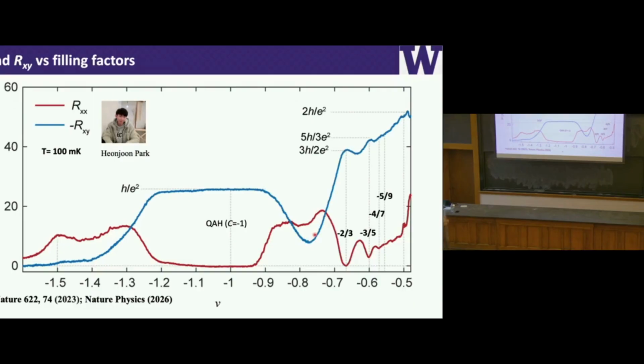So what it means is that it's a ferromagnetic metal phase, but with partial filling of a flat Chern band. And then we keep doping, and reach the 2/3 filling. Now we have a vanishing Rxx again with Rxy quantized at 3/2 of h over e squared. So that's my 2/3 FCI state. And as we continue, you will see that Rxx increases with dropping Rxy. Then eventually it is quantized again at 5/3, and we have another one, which is basically a 3/5 state, and also another dip at 4/7, etc.